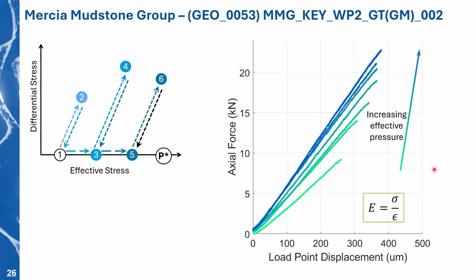So we see a slight change in the gradient of our lines. So from the green to the darker blue, I was increasing the effective pressure. So we're seeing this gradient of the axial force to the displacement increasing. So from this, we're actually able to start calculating some of our poroelastic parameters. So the one I've got here is the Young's modulus. So as I increase the effective pressure for this one, we're estimating Young's modulus between 8 and 25 GPa, which matches up reasonably well with other mudstones.